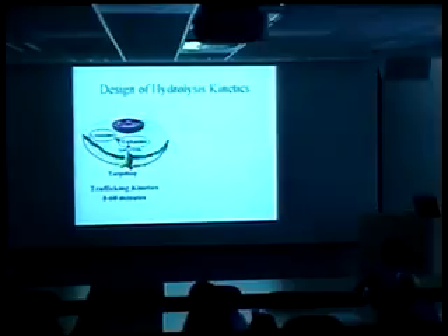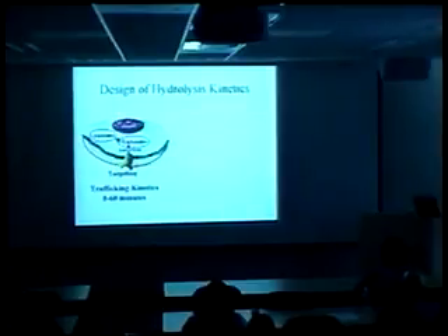The design, again, was really crucial here to couple it to the biology. And so the normal trafficking kinetics going from the endosome to the lysosome fall on the time scale of, say, 0 to 60 minutes. Okay? And so this is a time frame that you have to beat. And this is really a big challenge because at pH 7.4, it needs to be stable. But then within 30 to 60 minutes, as this is acidifying, that has a time aspect to it, then it needs to fall apart. Okay, so it has to fall apart fairly rapidly and yet be stable.